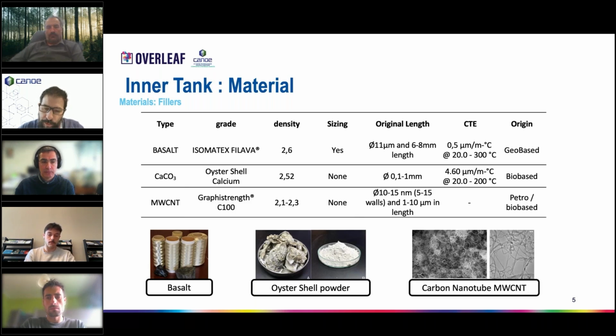And finally, we also tried some nano reinforcements, like carbon nanotubes, but multi-wall. The density is lower than the other ones, but still high for a carbon one. We used the Graphistrength C100 from Arkema, just to check if some nanofibers could enhance the mechanical resistance at very low temperature.